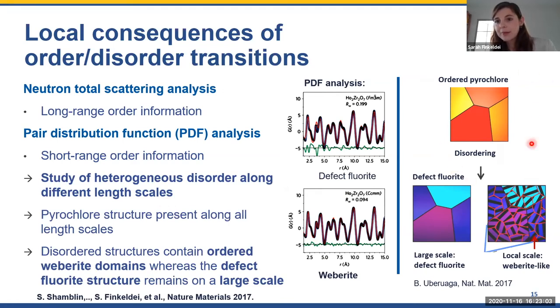So when we looked at a pyrochlore sample, and this is a graph that Dr. Blas Uberuaga from Los Alamos drew when he highlighted our Nature Materials article in the News and Views. And I think this is a nice way of explaining it. For a pyrochlore, we obtained information from the neutron total scattering, as well as from the PDF, about a pyrochlore structure. So the pyrochlore structure is present along all length scales. But when we start this disordering process and we look at a sample that by XRD looks like a defect fluorite, and by neutron total scattering analysis also looks like a defect fluorite sample, we found with the PDF analysis, where we are looking at the short range order, a higher ordering. So basically this order-disorder phenomenon happens differently along different length scales.